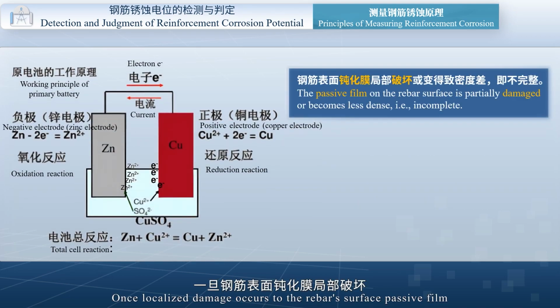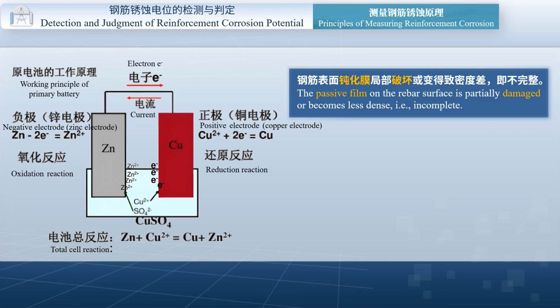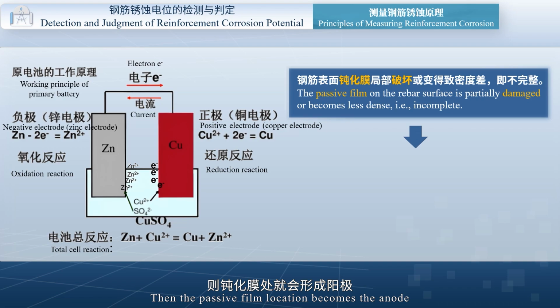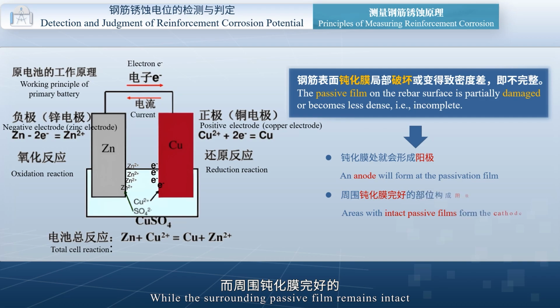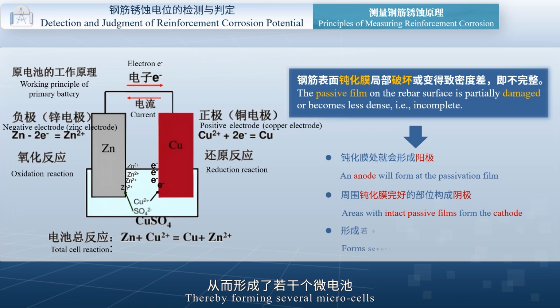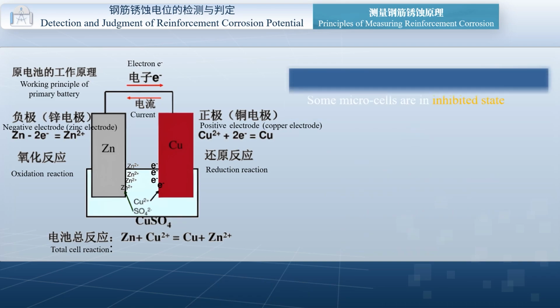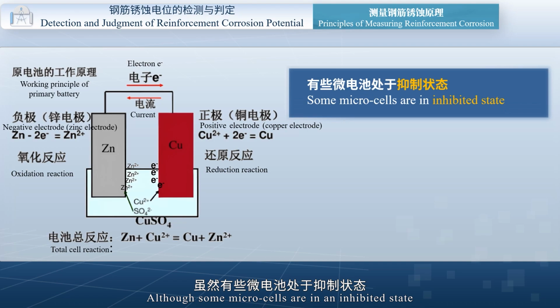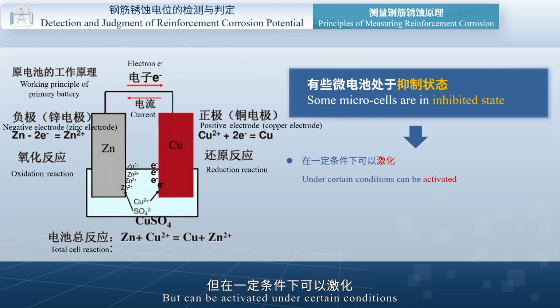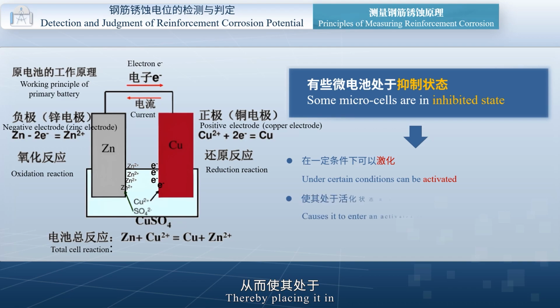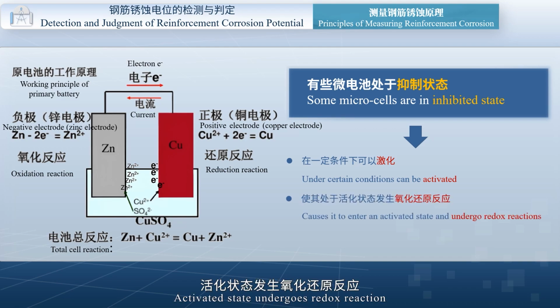Once localized damage occurs to the rebar's surface passive film, or it becomes poorly compacted or incomplete, then the passive film location becomes the anode, while the surrounding locations where the passive film remains intact form the cathode, thereby forming several microcells. Although some microcells are in an inhibited state, they can be activated under certain conditions, and in the activated state undergo redox reaction. This leads to reinforcement corrosion.